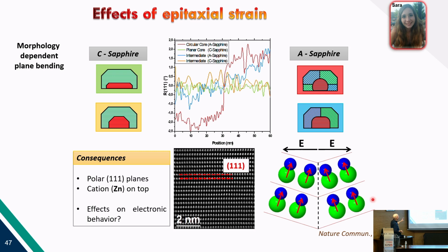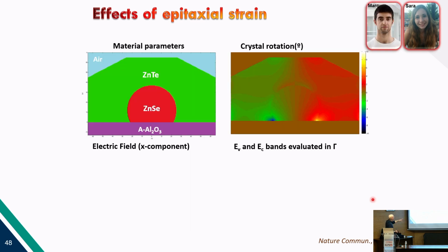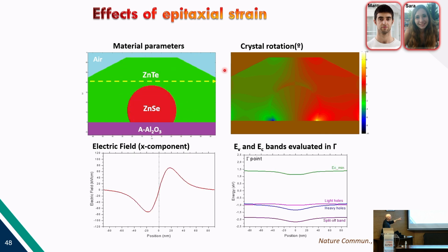So at the end, you are creating this potential barrier here, and you can always take your material, relax it, and see that, yes, this is what happens. It's trying to flex on both sides, and then, again, it's more or less comparable with the real. So that is the model, but this is the real case that you are getting. And then finally, you can calculate the potential, this electromagnetic barrier in the middle that is created by this flexing of the dipoles exactly in the middle part.